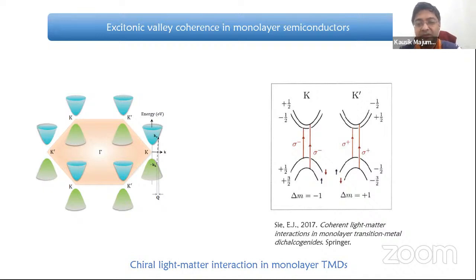So left-hand and right-hand circularly polarized light can be absorbed by two different valleys in these monolayers. Now, let's say you are exciting with linearly polarized light, which you can think of as a coherent superposition of sigma plus and sigma minus. Then you can generate a coherent state of these K and K prime valleys. However, the unfortunate part is that such valley coherence, which you can generate, quickly degrades. So the question is, how can you increase the time for which this coherence is maintained? That's the focus of this talk.